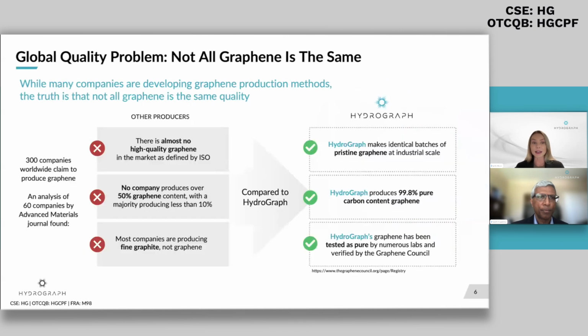So this is slightly dated. This is from 2017, but I think much of this still rings very true today, and anyone that's involved in the graphene industry can easily confirm this. So this was from the journal Advanced Materials. They studied all of the graphene in the market. We did not participate in this study. And overwhelmingly, they found that there is almost no high quality graphene in the market as defined by the ISO. No company produces over 50% graphene content, with a majority producing less than 10%.